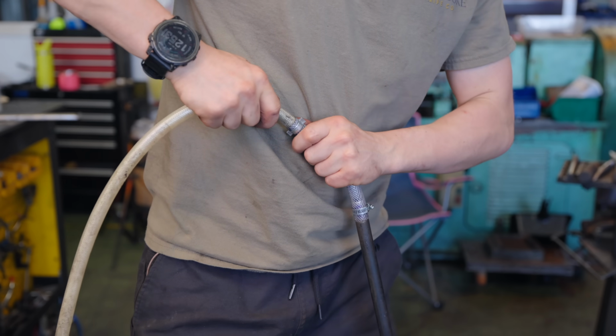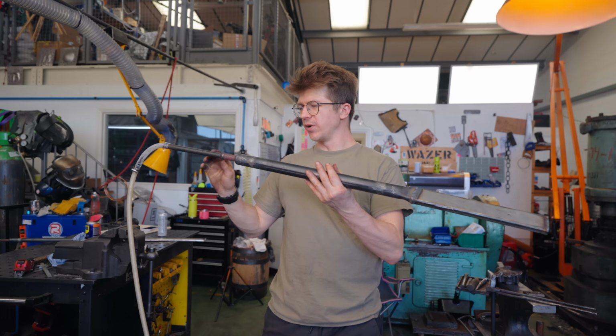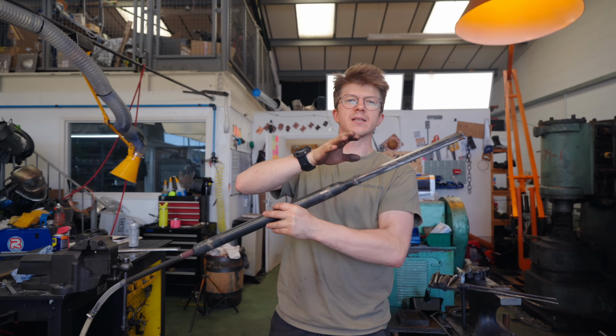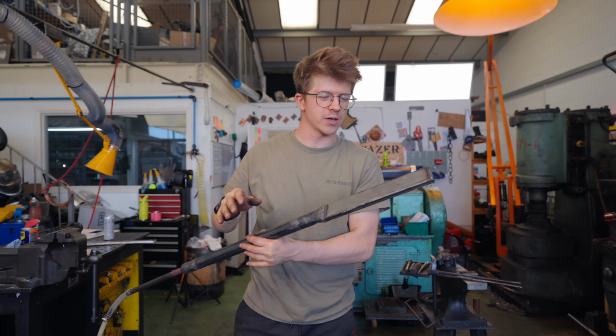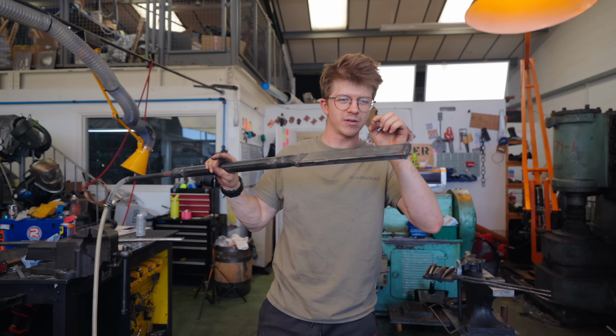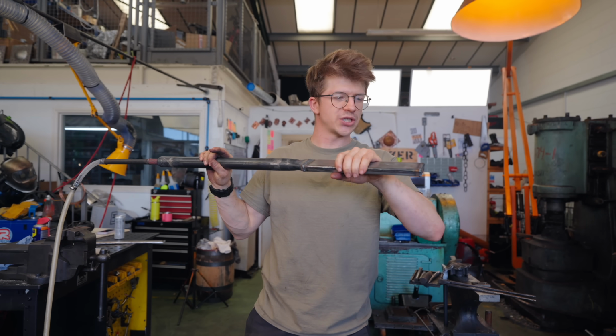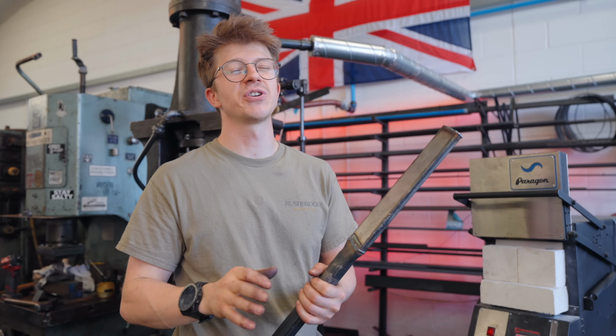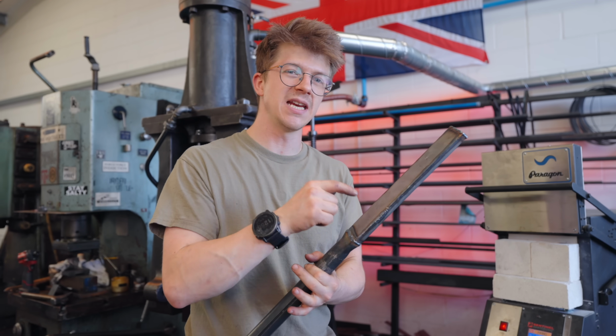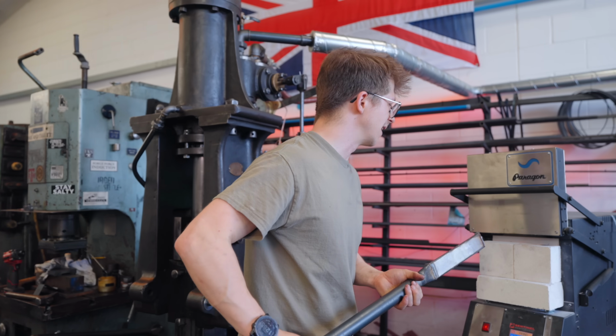There's our argon. Plug that in here. And what we're doing, we are pumping argon through this billet so that we're hopefully going to evacuate all of the oxygen. I can then turn the pressure down and just have a little trickle, so we've got a positive pressure in here. Any oxygen in here at a high temperature is going to be a bad time because titanium oxidizes very strongly at temperature.